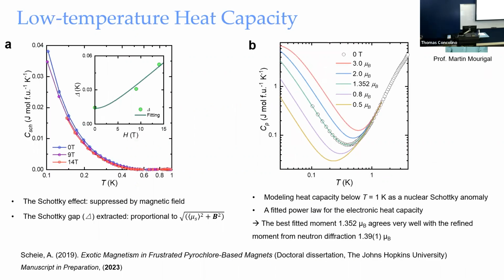So we would like to look a little bit deeper into the low temperature regime, and Martin Mourigal helped us with the measurements. So here are the low temperature heat capacity measurements. I want to show you on the left the Schottky anomaly, and you see actually the Schottky effect is suppressed by magnetic field. See, it's at 14 Tesla, 9 and 0. And we do the fitting here, so we can extract the Schottky gap from the fitting, and it is proportional to the contribution from the magnetic moment and also the applied field.